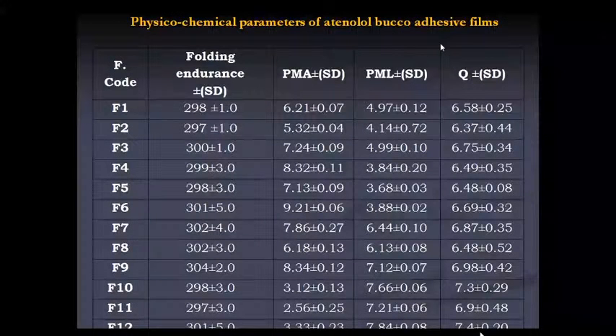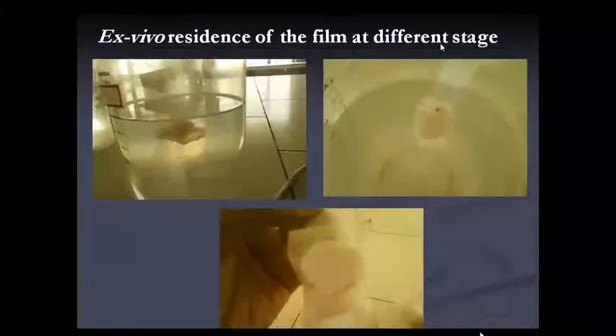This is the beaker. In that, we have taken phosphate buffer pH 6.8, which is similar to salivary pH. A freshly cut porcine buccal mucosa got from the slaughterhouse. The 2 centimeter size film is stuck to the buccal mucosa here. This buccal mucosa is attached, and the whole setup is immersed in the buffer. And we have monitored for around 8 hours. The time taken for detachment of the film from the mucosa is known as the ex vivo residence time. So when you are making the film, you compulsorily need to do this test.